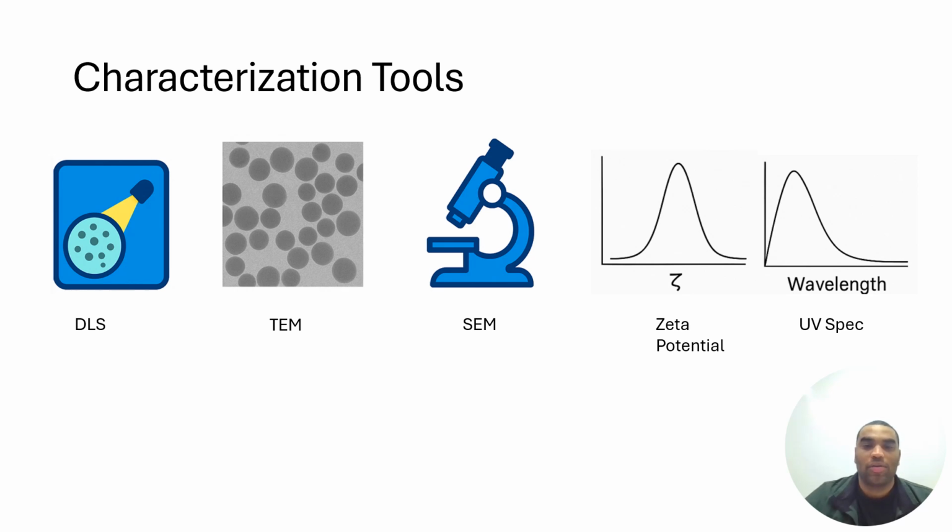Transmission electron microscopy, TEM, then was used to visualize the internal core, shell structure, and morphology of the nanoparticles. These high-resolution images helped verify that the self-assembled micelles formed correctly and consistently.